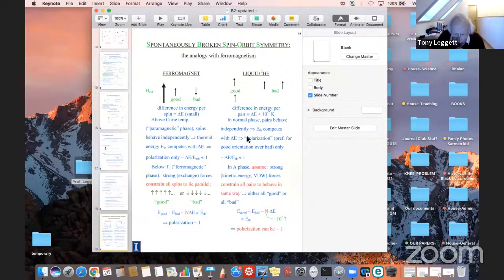There seems to be a general preference for strongly layered materials. All the cuprate high temperature superconductors are indeed strongly layered. They have these copper oxide planes, which are very strongly two-dimensional in nature. And the same is also true of some of these other more recent materials, ferropnictides, strontium ruthenate, one or two others. People have got all sorts of prescriptions for trying to predict transition temperatures, but we really haven't been so good at that. In fact, the transition temperatures of the cuprates range over something like an order of magnitude, from something like 10 degrees absolute to about 150 degrees absolute.